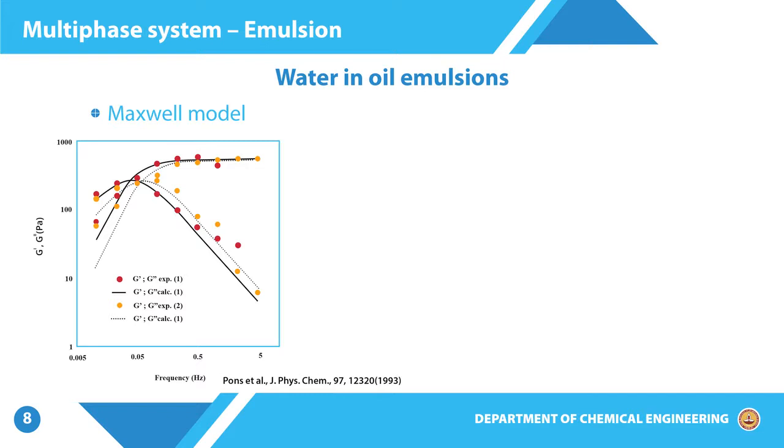Even though this shows a glassy response in terms of what we observe here, we should remember that the material need not be glassy in the sense that it is not a hard glassy material the way we usually think of a glass material. Given that we are only probing the material in a limited frequency range, in this case 0.05 to 5, we see that in this frequency range the material seems to show frozen responses.